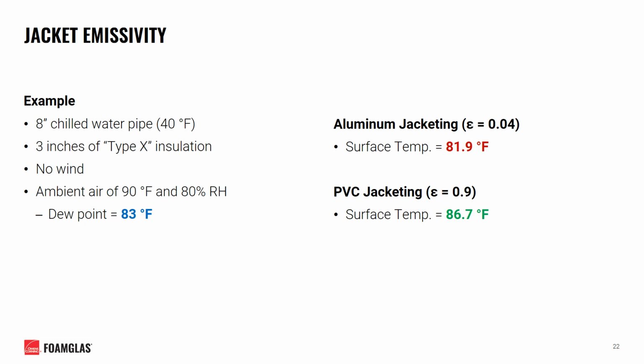However, when we take the same system and cover it with our PVC jacketing, more heat from the environment is allowed to transfer into the jacket surface, giving us a surface temperature of 86.7 degrees F, safely above the dew point where surface condensation will become an issue.